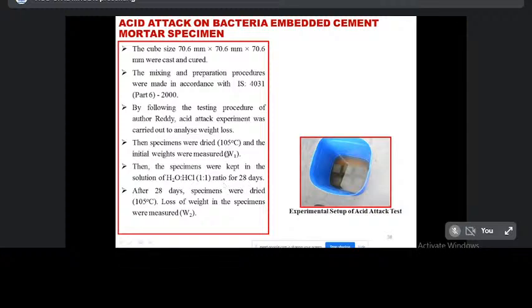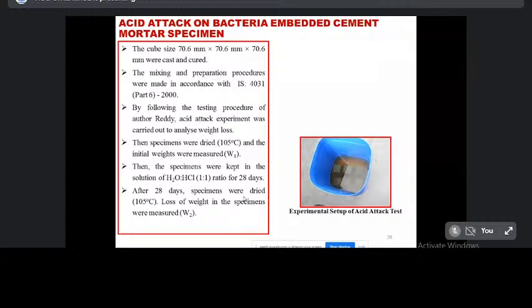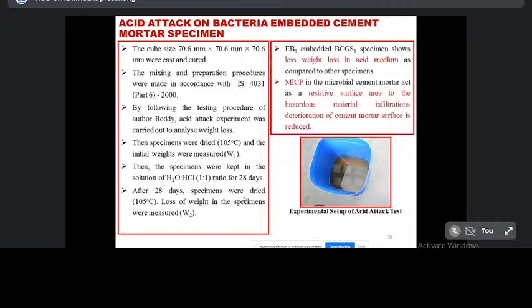Then this initially weighed specimen is immersed into this acid solution for 28 days. After 28 days, the specimens were dried at 105 degrees centigrade. The loss of weight of the specimen was measured. That measurement is W2. The EB1 embedded BCGS1 specimen shows less weight loss in acid medium as compared to other specimens. MICP in the microbial cement mortar acts as a resistive surface against hazardous material infiltration, so deterioration of the cement mortar surface is reduced. Actually, this MICP prevents the penetration of acid into the cement mortar specimen. This is the formula I have used to find the acid attack: W2 minus W1 divided by W1 times 100.